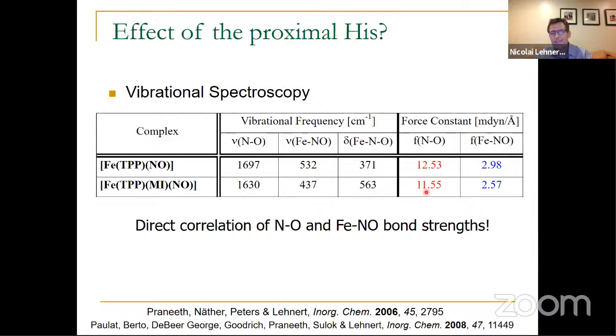And what you see here is that in both cases, the NO bond and the iron NO bond become weaker in the 6-coordinate complex. So when you invert the process in a way, you start with the 5-coordinate complex and you bind imidazole in trans position to NO, both the iron NO bond and the NO bond become weaker. And you can see this in the vibrational frequencies, and you can see that also in the force constants, right? And so we call this a direct correlation of the NO and iron NO bond strengths. And this direct correlation is a hallmark of bonding. I'll show this to you in a second, right?